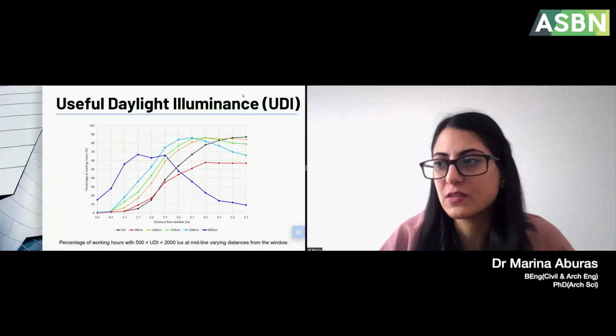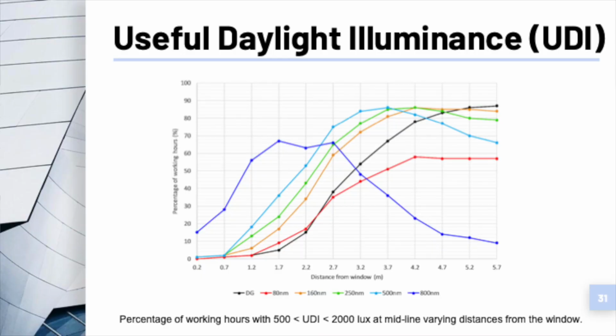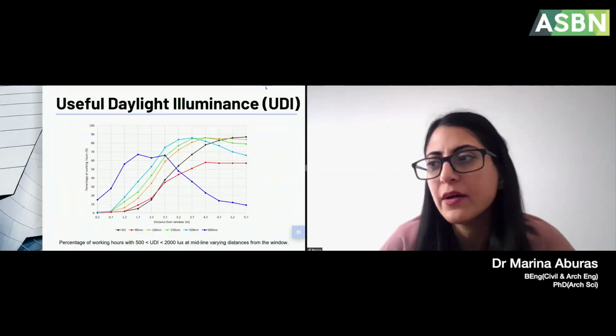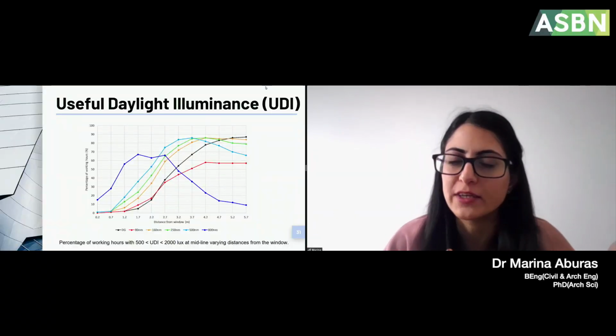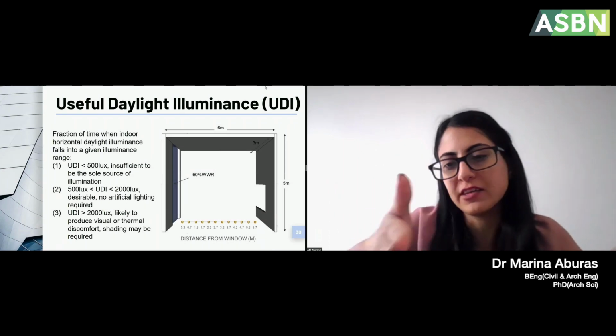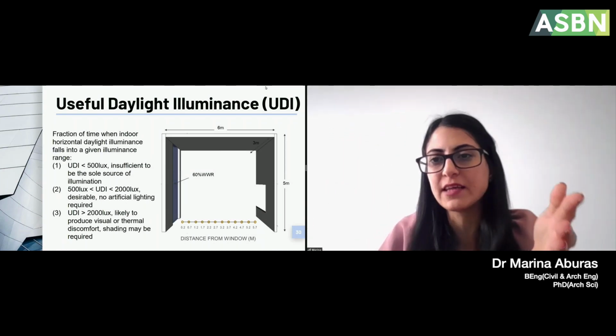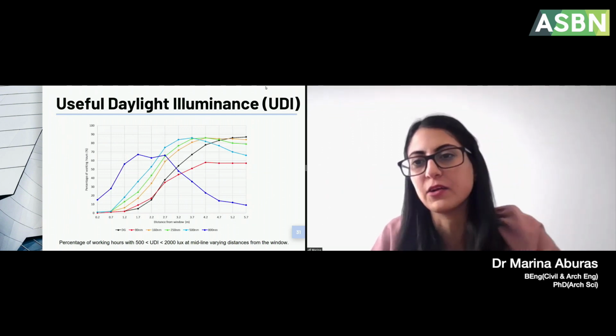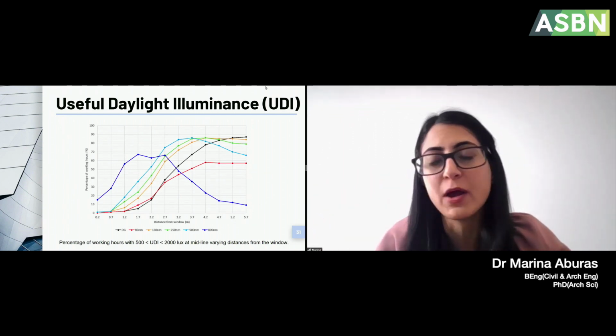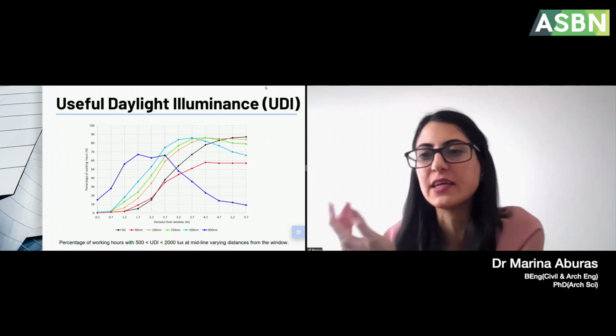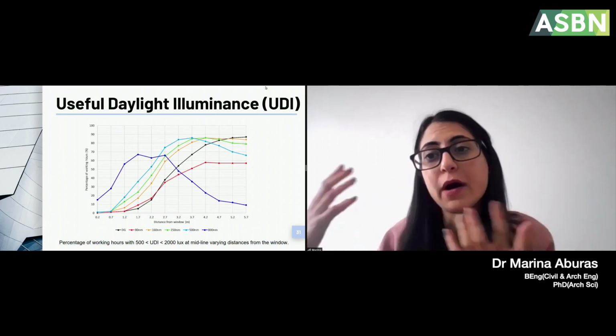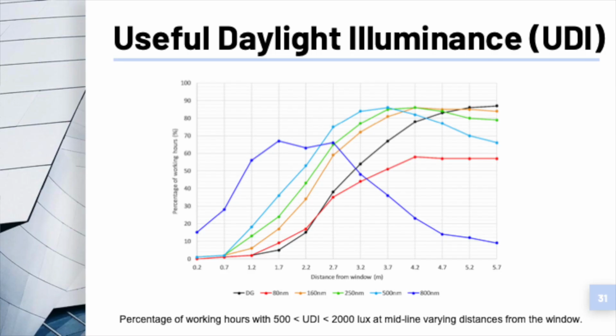So you can see the different spread of the percentage hours in that comfortable band, where the majority of the thermochromic windows could provide improved daylighting in comparison to the double glazing and the black line there. But it's interesting that that thicker thermochromic coating in the dark blue has its most desirable range closer to the window. So you've got the different distances from the window with the window placed on the left-hand side, and that corresponds exactly to the graph there. So depending on which coating you use, you might want to put a desk right up against the window or a desk closer to the middle of the space.